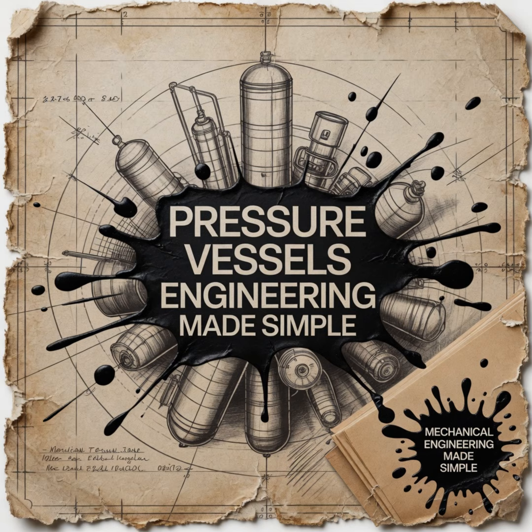A very dangerous one. If you have a razor-thin lack of fusion defect, a crack where the metal didn't bond, but there's no actual gap or void, and the X-ray beam hits it straight on, the radiation passes through the surrounding steel and completely misses the crack. The film looks clean, but there's a lethal defect inside. Which is terrifying. And that's exactly where UT, ultrasonic testing, shines.